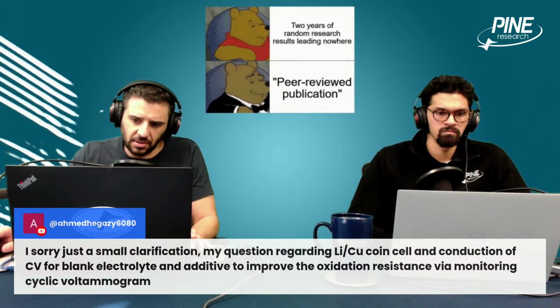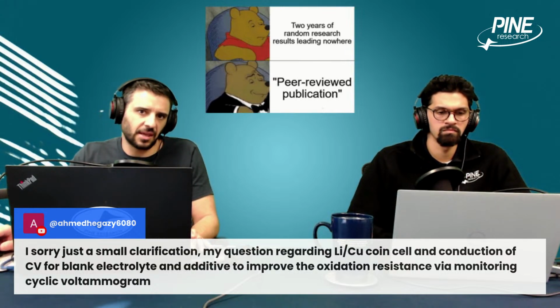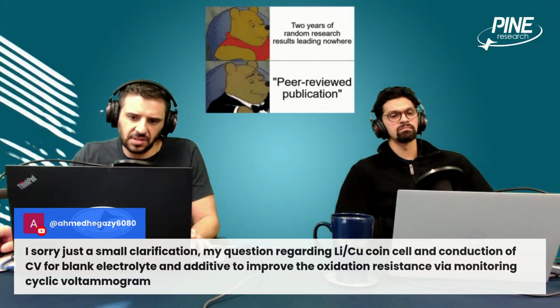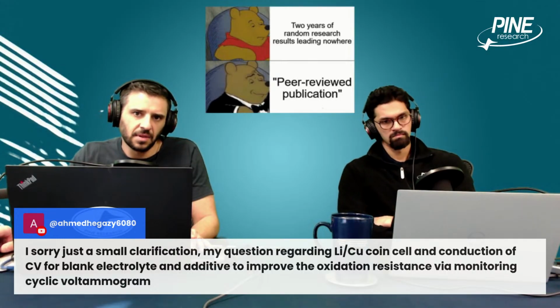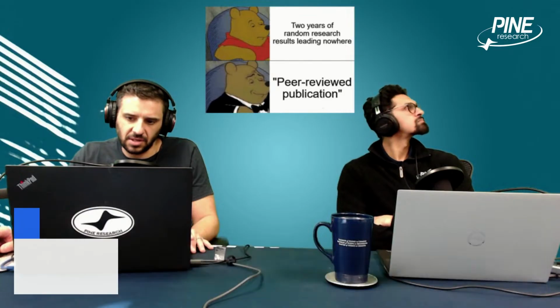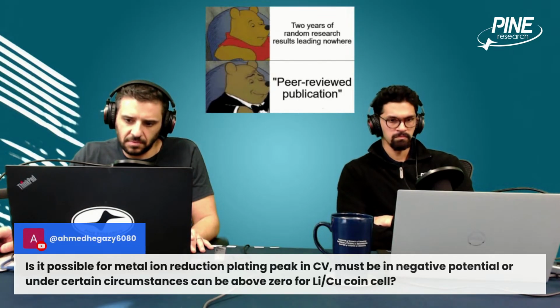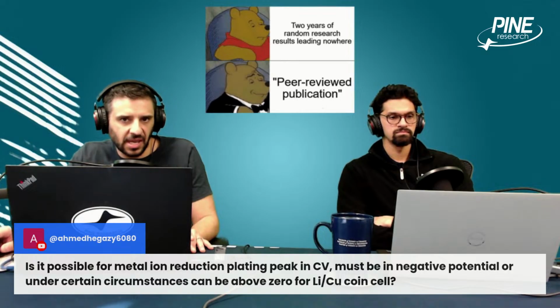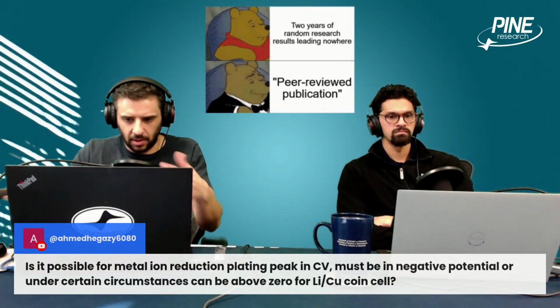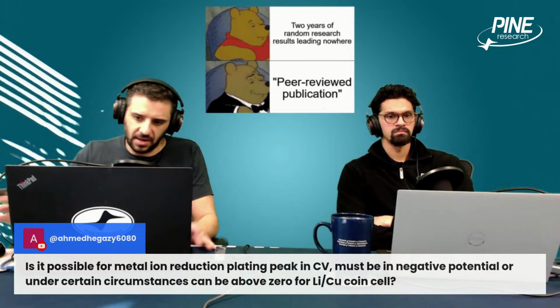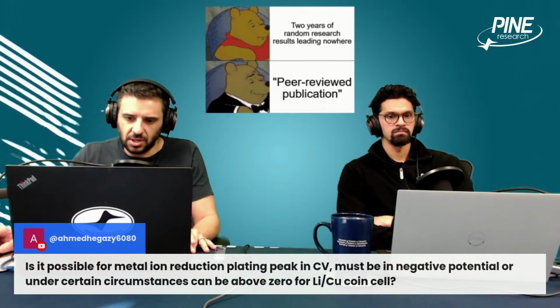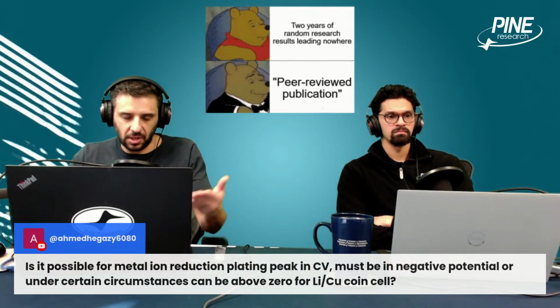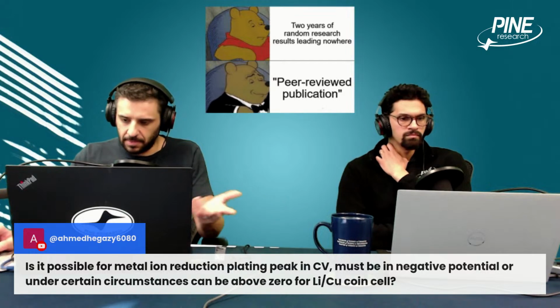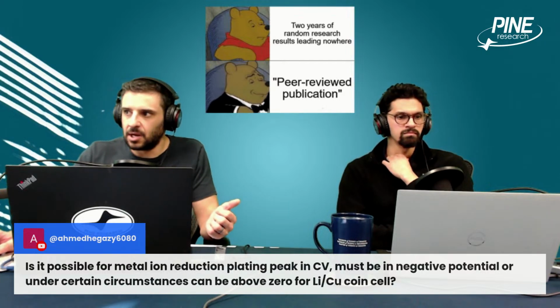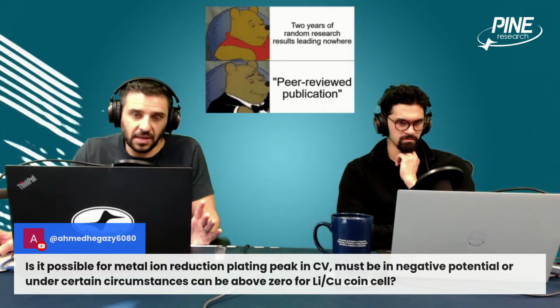I would also probably assume that something like impedance would be better to study the oxidation resistance than cyclic voltammetry. Cyclic voltammetry, to your last question, is probably more useful for figuring out where the peak might be. If what I said is not true, and maybe it does happen at negative potential for whatever situation you're in here, CV is going to be good for determining where that potential will occur, finding that peak, and then maybe pinpointing the potential at which something will happen in your system.